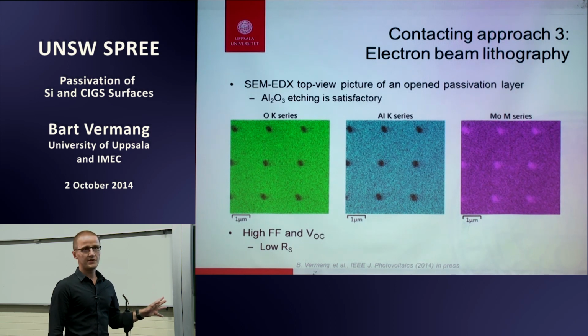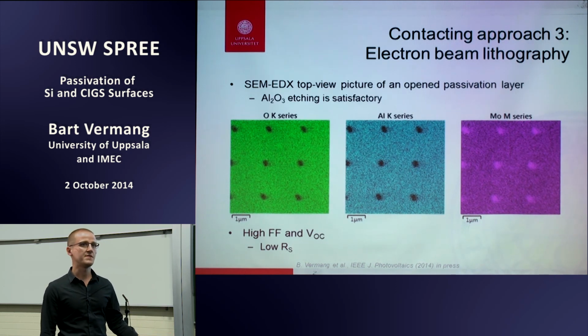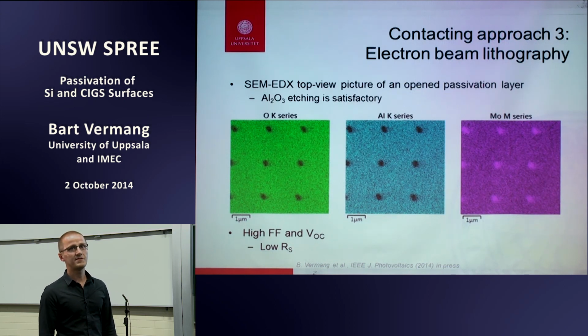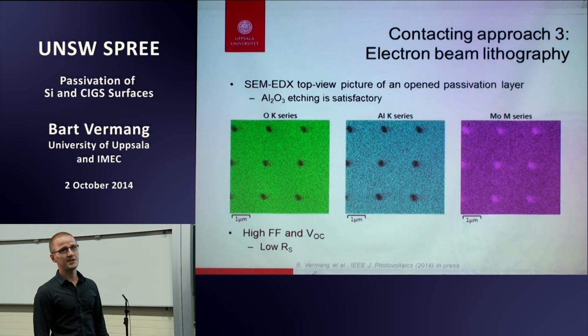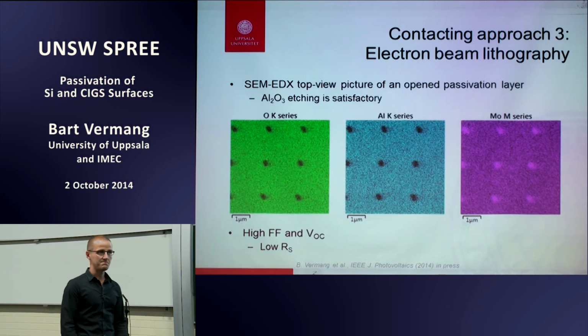I'm 100% sure because of the high fill factors. We would not have high fill factors. We have fill factors up to 81%. You would not have this if you don't have molybdenum selenide at the interface. That's my opinion.